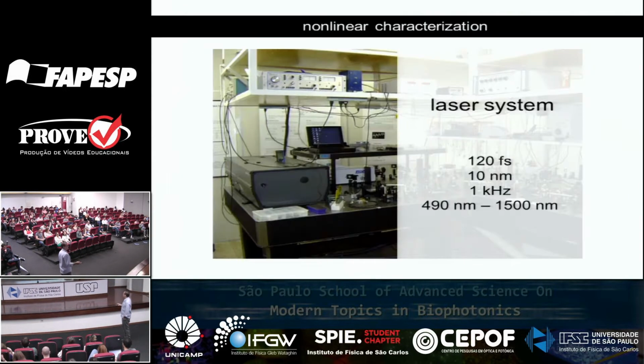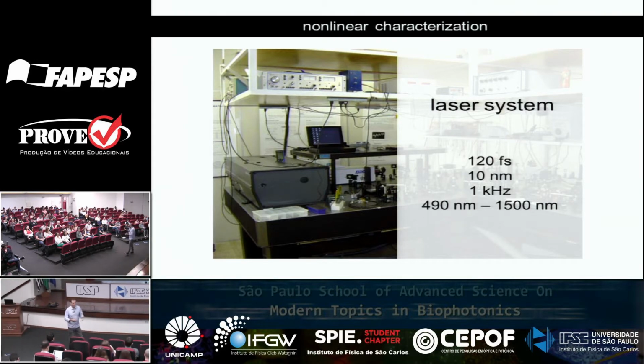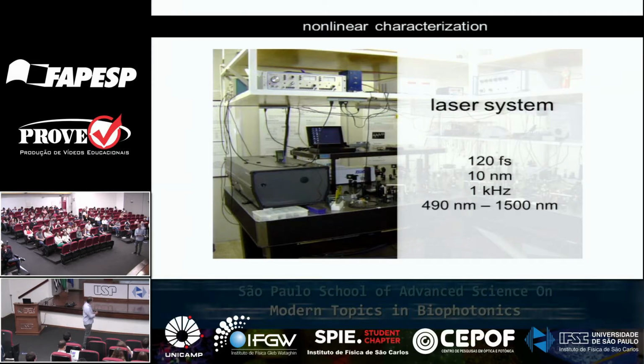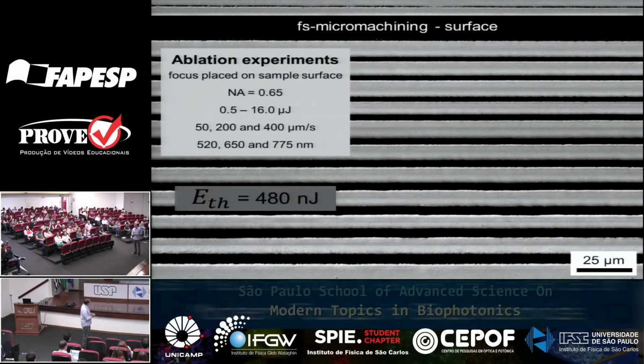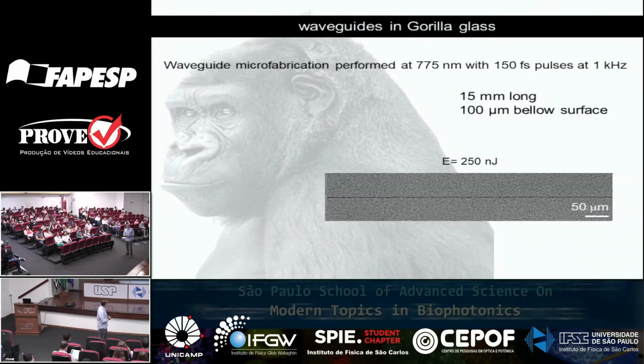So in this case, just to give you an idea, we are using a 1 kilohertz laser. Depending on the glass, you might go with the megahertz, but the megahertz has a smaller energy per pulse. The point is, because it's Gorilla Glass, if you try to micromachine using only nanojoules of energy, it doesn't work. So you need microjoules because the glass is very resistant. So that's why we use the femtosecond laser with the kilohertz. So those are some lines we fabricated in Gorilla Glass just to illustrate. And the threshold energy that we need to fabricate on Gorilla Glass is on the order of 500 nanojoules, so half of a microjoule, okay?